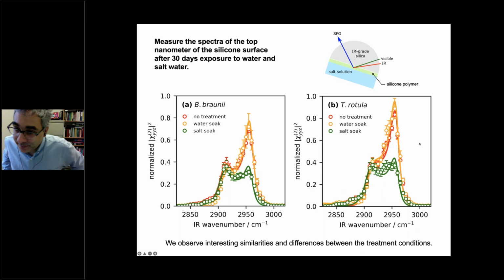So when we do that experiment, this is basically the result that we get. We see something which is a vibrational spectrum because we're using infrared light. So just like I showed you before, we have this methyl group symmetric stretch, we have this methyl group anti-symmetric stretch, but what's really special is that all of the data points that you can see that make up these spectra came from just a nanometer at the top of the surface. And the first thing we can see is, unlike that 1 micron length scale probe, which was 1,000 times deeper than what I'm showing you here, now we see a substantial difference between the different environmental conditions, particularly with respect to salt.